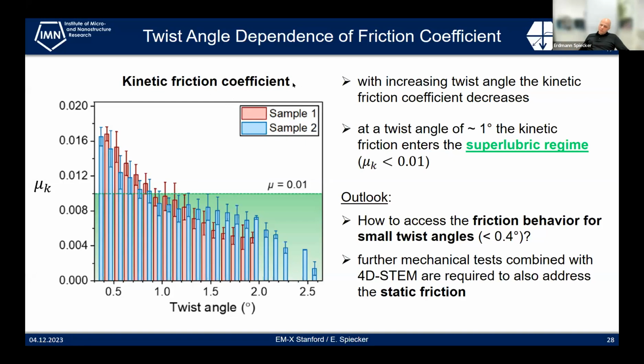But of course, this can be performed also in 4D STEM mode and virtual aperture reconstruction. That's true. Also, it's the in situ. If you're doing in situ, then the TEM mode is still superior. As I mentioned, the movement of the film or the sliding is too fast to capture, even with the dark field imaging. As you can imagine, a stick-slip motion is very fast. So only if it's arrested again, we can investigate it.